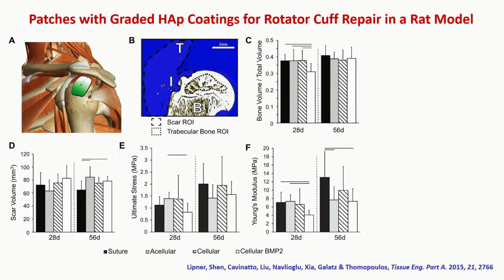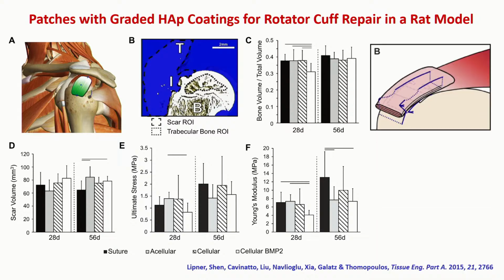And then we analyzed this problem. We realized maybe this kind of patch is not a good idea to use at all. When you apply this patch onto the repair site, the stem cells in the surroundings can only really see the surface, okay? They don't really see the region between the tendon and the bone. So that's why eventually the junction is not going to be repaired as we would expect.